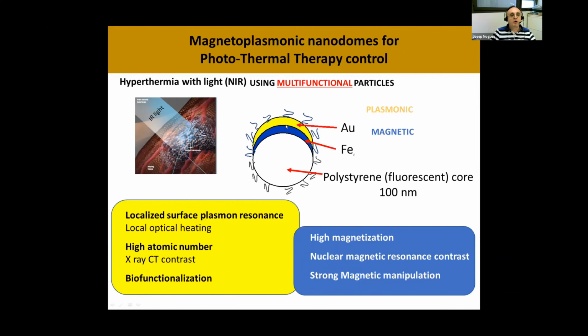So what's the role of the gold layer? The gold has a localized surface plasmon, which we can use for optical heating. Then it also has a high atomic number, which can be used for X-ray computer tomography contrast. And it's very easy to biofunctionalize the gold layer.